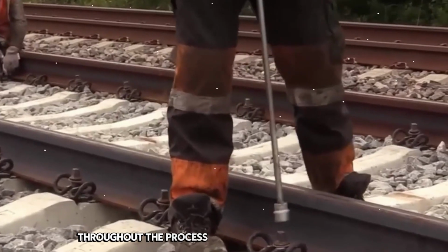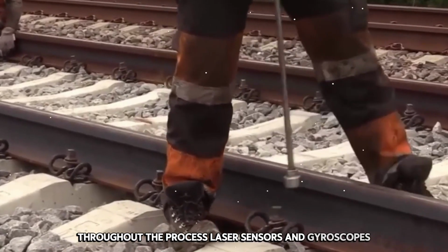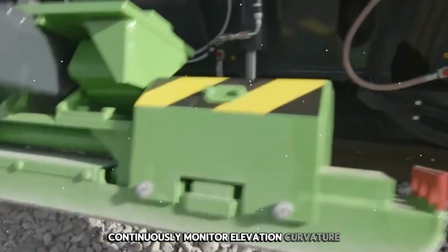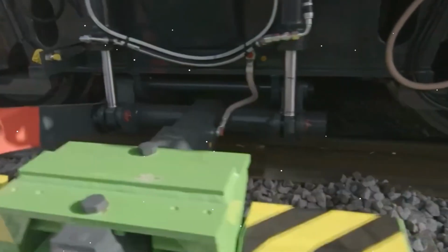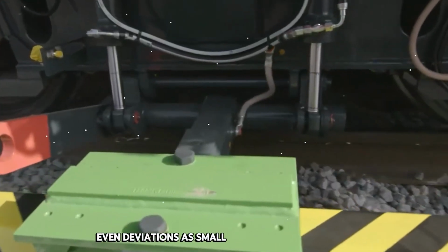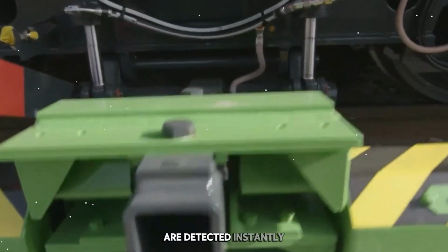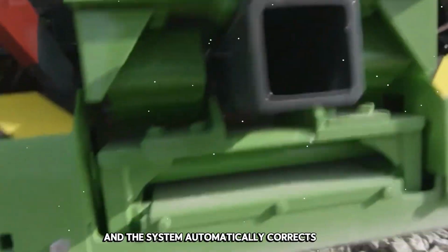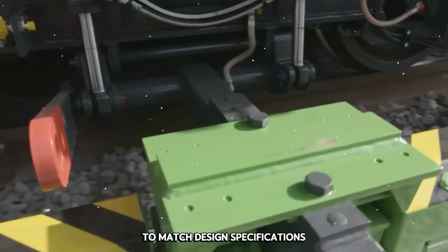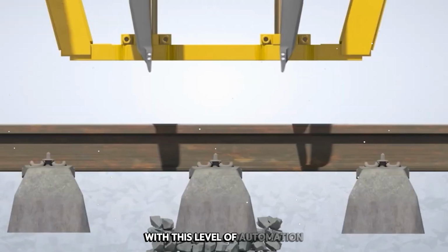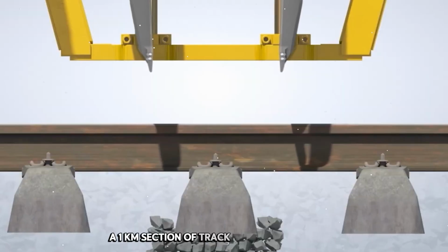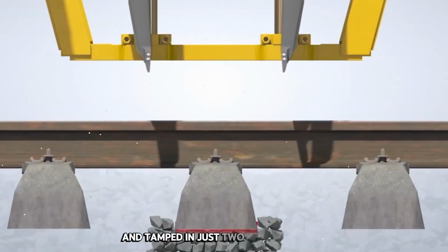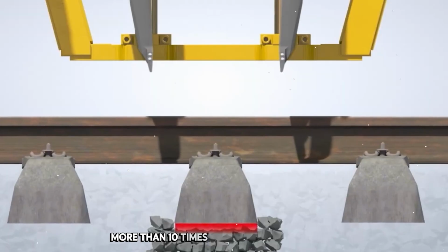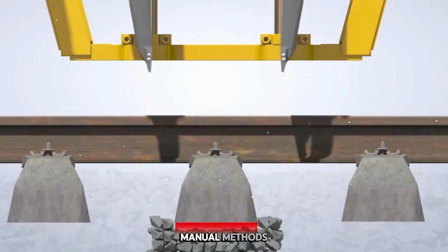Throughout the process, laser sensors and gyroscopes continuously monitor elevation, curvature, tilt, and alignment. Even deviations as small as 1/10 of an inch are detected instantly, and the system automatically corrects them to match design specifications. With this level of automation, a 1-kilometer section of track can be fully aligned and tamped in just 2 to 3 hours, more than 10 times faster than traditional manual methods.